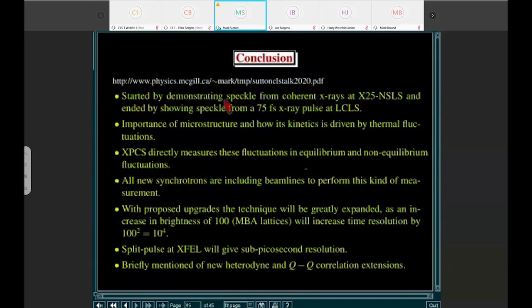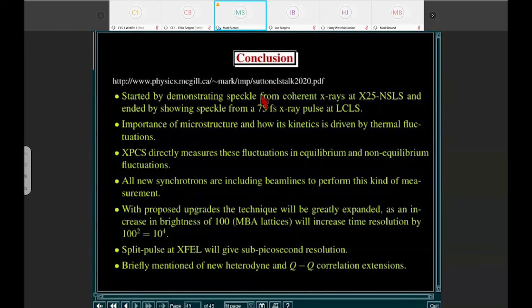Let me make the conclusions first of all about the XPCS. I started by demonstrating a static speckle pattern, which we took at a wiggler line at the X25 beamline at NSLS. And I ended by showing a static speckle pattern which was taken in 75 femtoseconds, averaged over many pulses, at the LCLS. So that's a nice set of bookmarks of the progress that we've been making in XPCS. And we now have a wavefront splitting split and delay monochromator. As a matter of fact, this weekend we'll be doing experiments at LCLS using it.